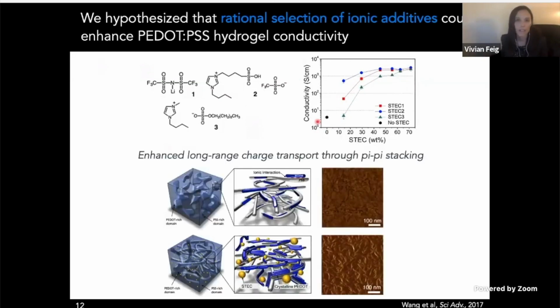And these conductivity enhancements correlate to a change in the film morphology from kind of this ill-defined grain structure to having these extended fiber-like morphologies where the fibers are comprised of crystalline PEDOT units whose crystal spacing distance is comparable to the pi-pi stacking interaction distance between different conjugated PEDOT polymers.